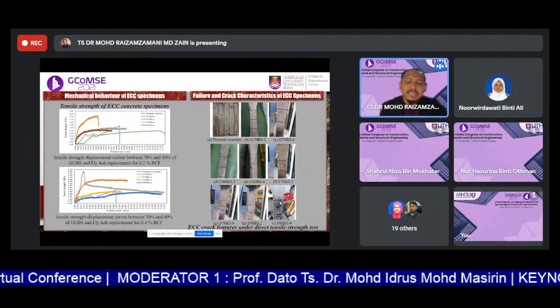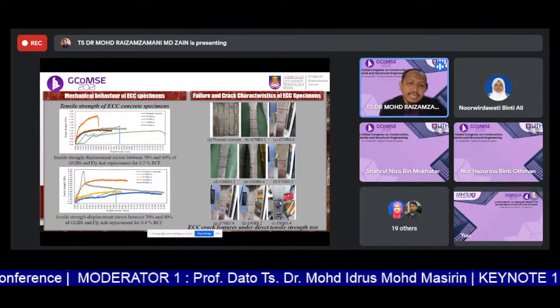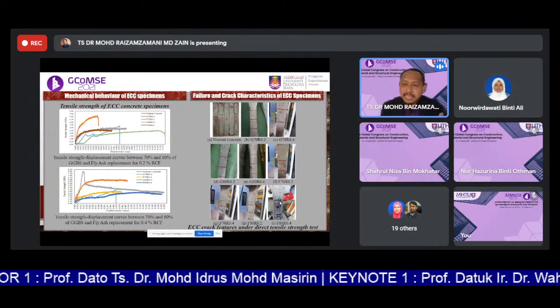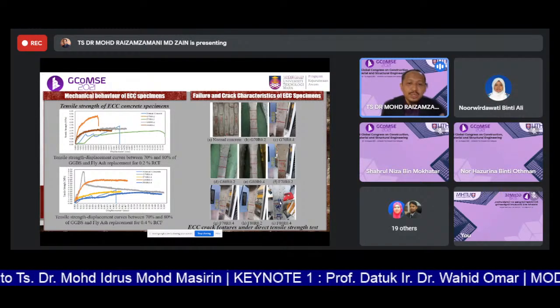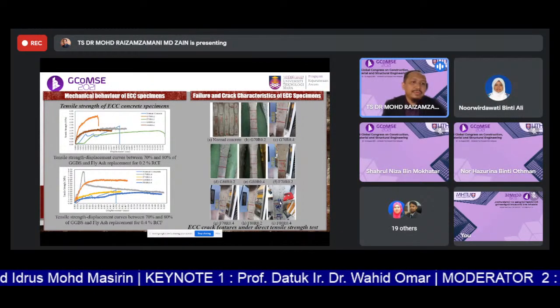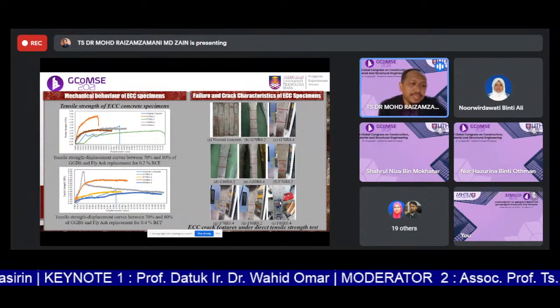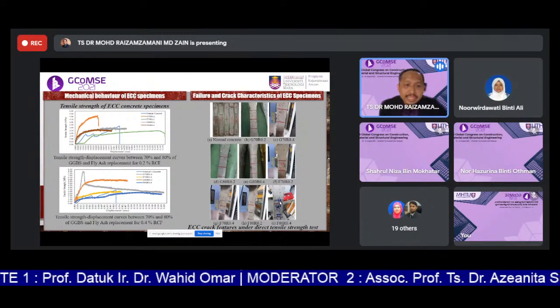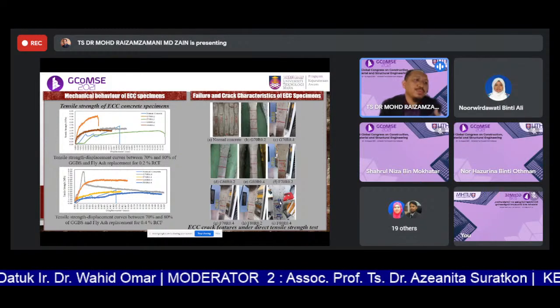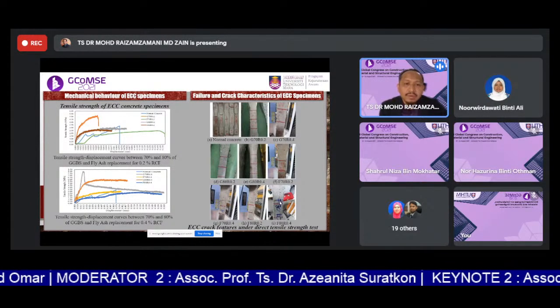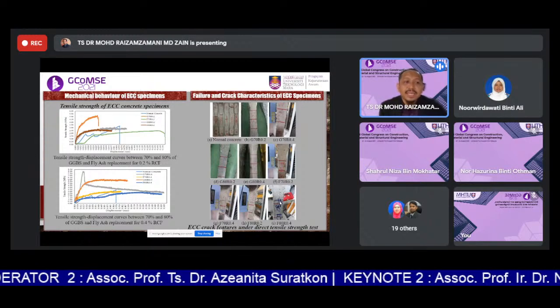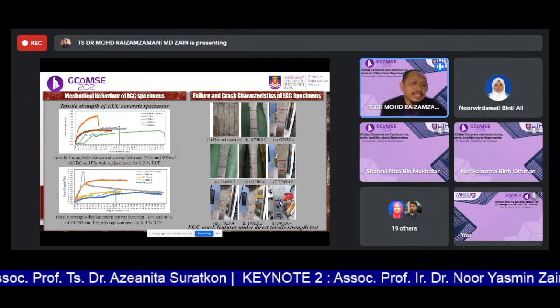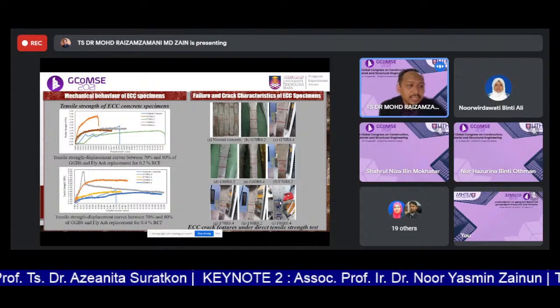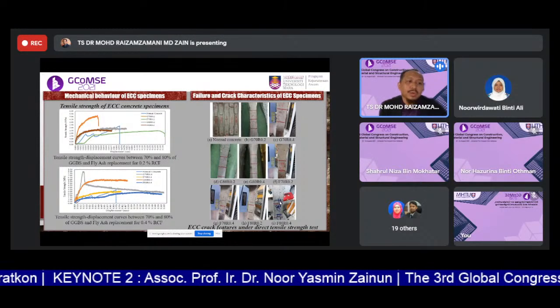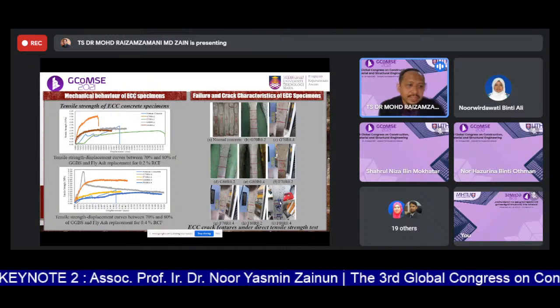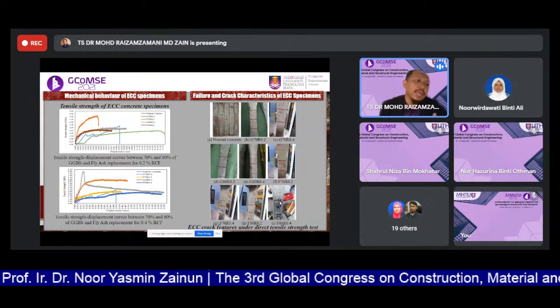And the second figure denotes the tensile strength or displacement curve between 70 and 80% of GGBS and fly ash replacement for 0.4 BCF. If we look at the first figure here, it demonstrates that GGBS cement combinations, for example G70 0.2, have the higher tensile strength values of around 5.26 MPa when compared to the fly ash cement combinations, F70 0.2 here. And then also the normal concrete, which has the lowest values of 2.47 MPa and also 3.33 MPa respectively.